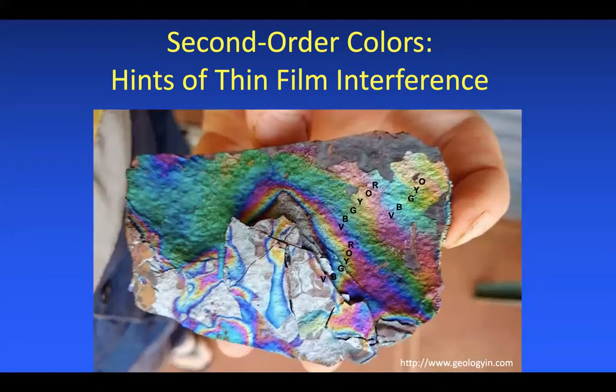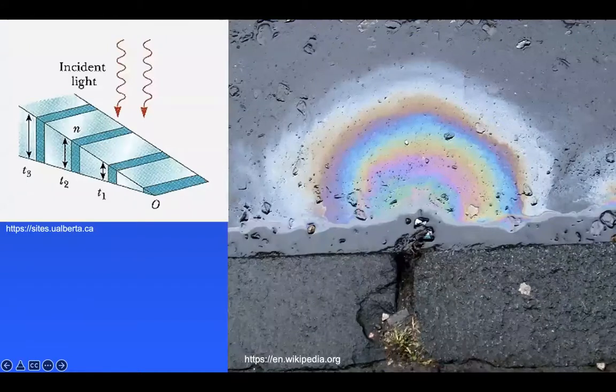And when I was examining these kinds of turgite specimens, one thing that really struck me was that there was a texture here that looked a lot like thin film interference. And in particular, what I noticed is that one saw many orders of interference. Rainbows we think of as consisting of this Roy G. Biv coloration. And we can see many iterations of these Roy G. Biv sequences here.